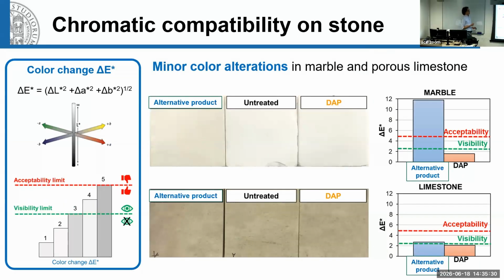As I mentioned, it's important not to change the color of the substrate. This was the case. Here, for instance, you can see a comparison between the DAP treatment that we developed and the most commonly used alternative commercial product. I think in this case, it's possible to see on the screen that the marble becomes gray, which is something that, of course, you don't want in your monument.